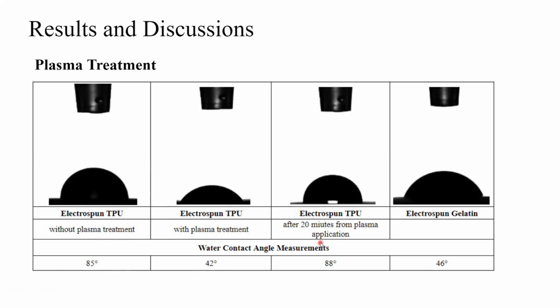However, after 20 minutes from plasma treatment, its contact angle measurement increases to 88 degrees, and again, it becomes more hydrophobic. Because of this, gelatin should be electrospun onto the TPU shortly after the plasma treatment. Lastly, the contact angle measurement of gelatin is 46 degrees. It proves that gelatin is hydrophilic compared to TPU.